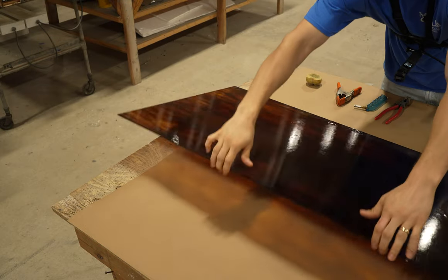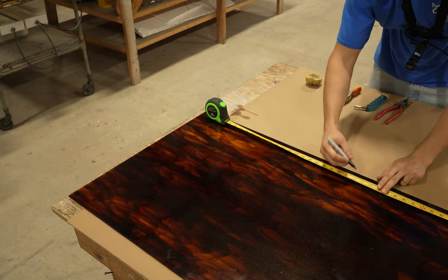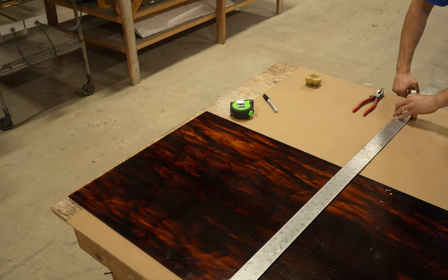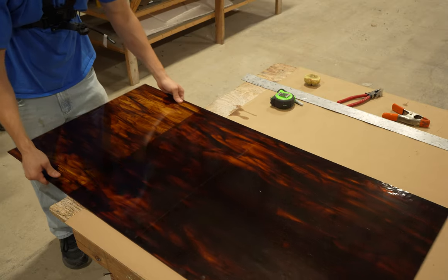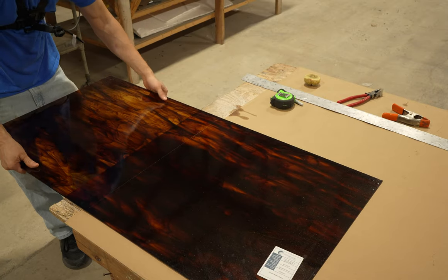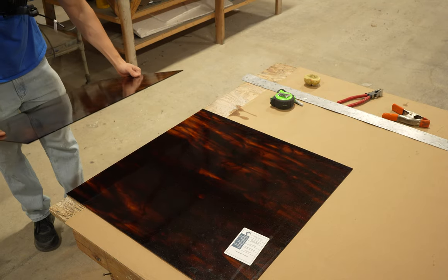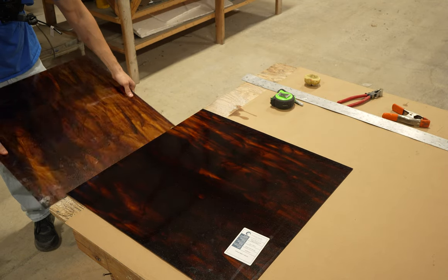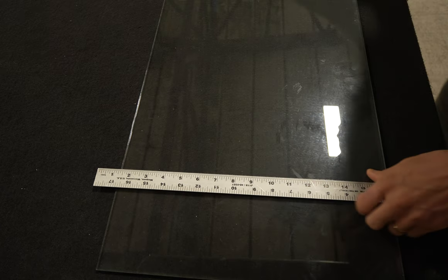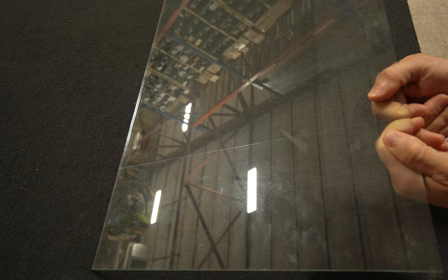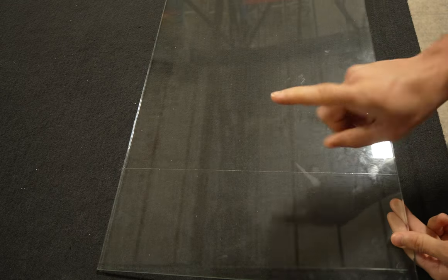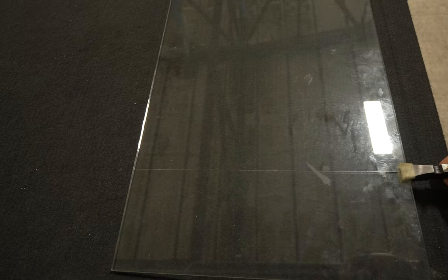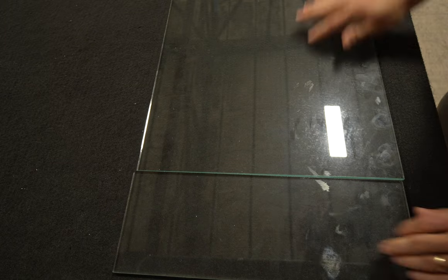For the last piece we'll be doing the straight edge technique once again but we'll be breaking the glass a little differently. Once the glass has been scored we'll pick up the sheet and drag it to the edge. We will align the score line with the edge of the table and pick it up about one to two inches off the surface of the table. Then we'll rapidly lower the sheet where the edge of the table will create enough force to separate the sheet. I normally use my hands because it's one less step to reach for the running pliers. However if I am cutting thicker glass I'll pretty much always use the running pliers because it requires far more force to break let's just say a quarter inch thick glass versus a one eighth inch thick glass.